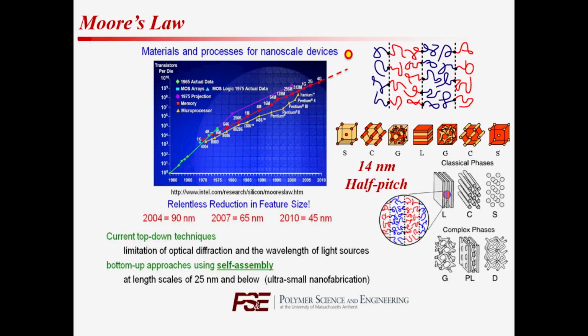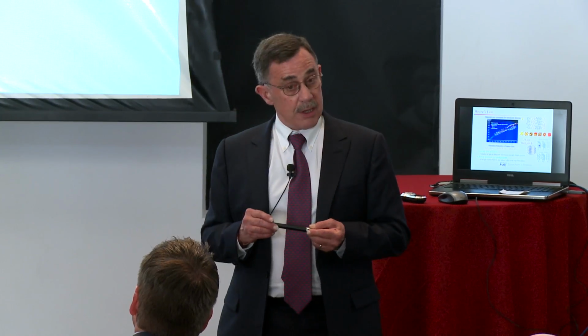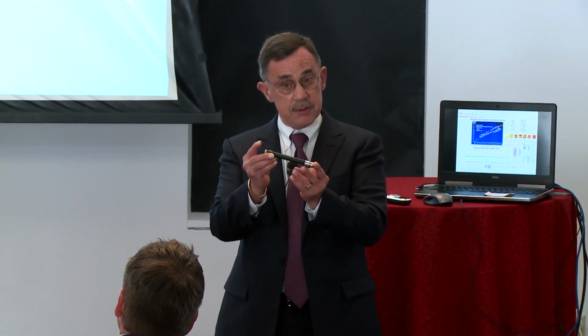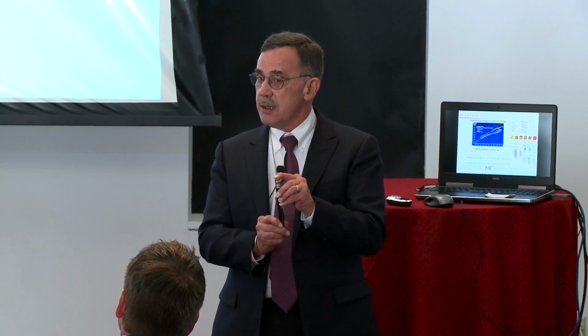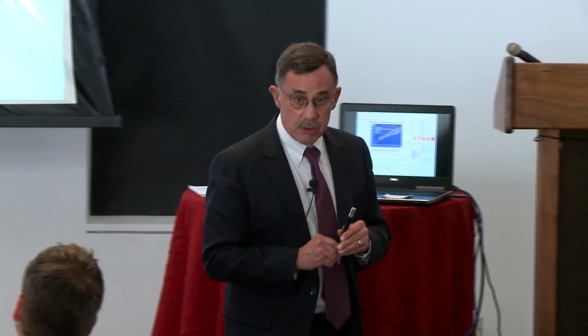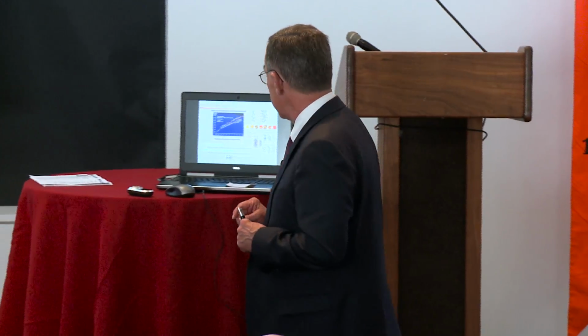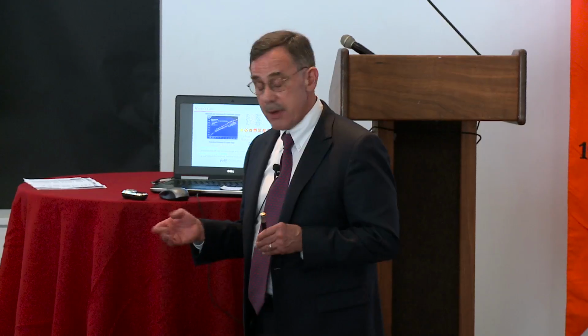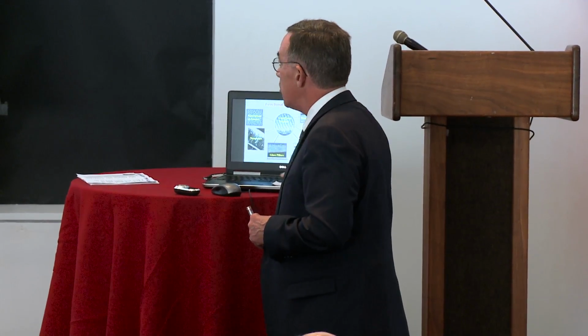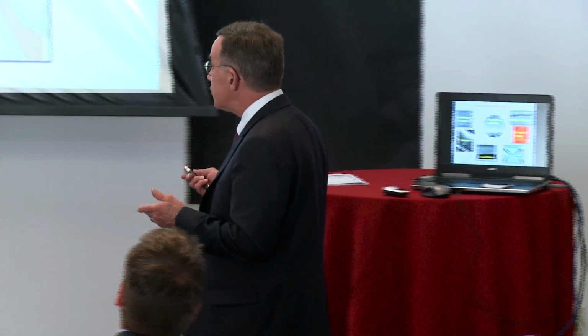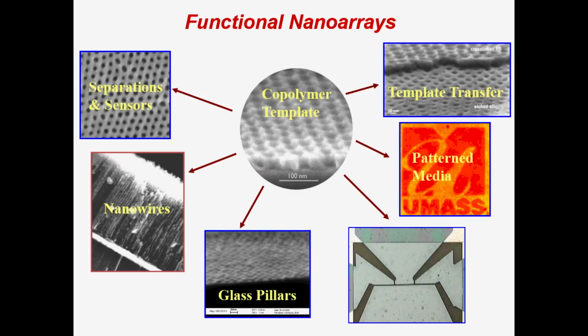The trick is we need to be able to control how these domains, let's say we had cylinders, how these cylinders are oriented in the film, whether they're parallel to a surface or they stand vertically. Because if I can control the orientation of these structures, and if I can control the overall lateral ordering, the types of applications are going to be immense. And this just shows you a couple. So this happens to be a block copolymer where I have all cylinders standing vertically, and I've removed the cylinders. So now I have holes.